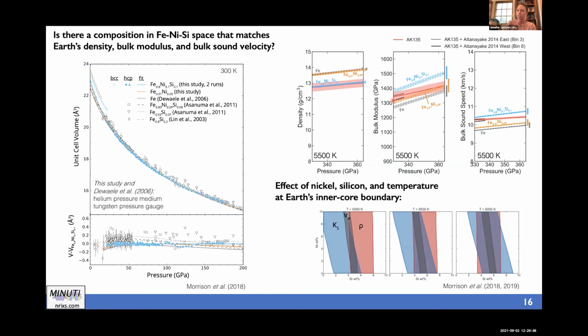But if we look at just the inner core boundary, we see that depending on the temperature, there's a tighter constraint on the low end. If we just consider nickel and silicon, we see this overlap here. But at higher temperatures, say assuming 6,000 Kelvin, there's quite a range of nickel and silicon contents that can explain, say, AK-135, which is one of the 1D models for Earth's core.